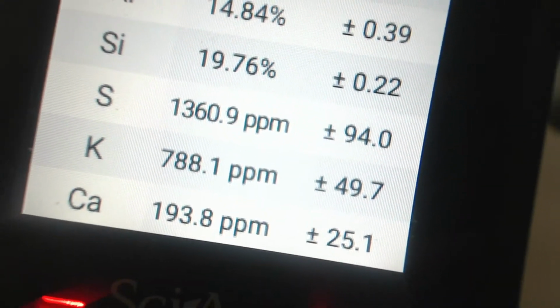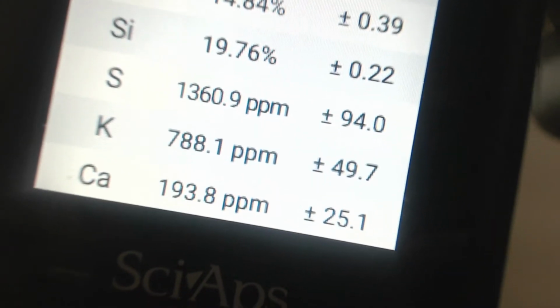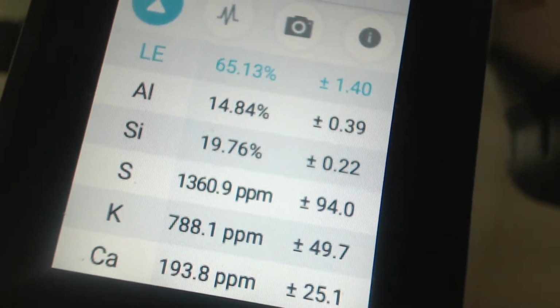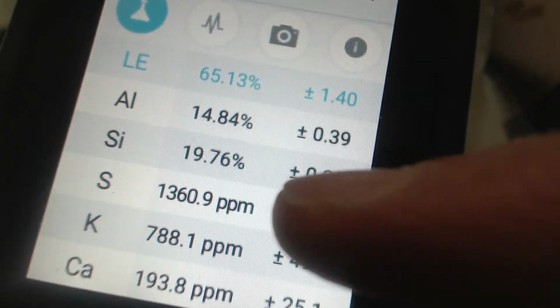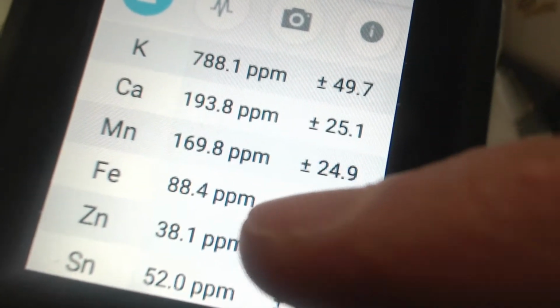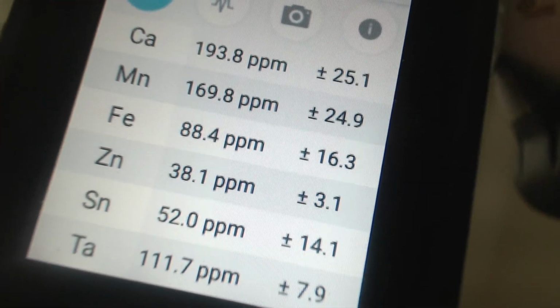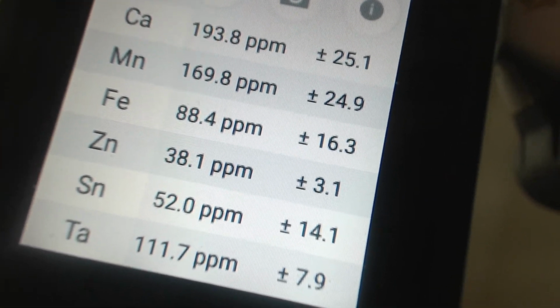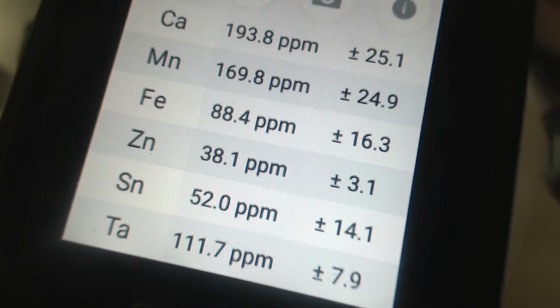So first off, you see aluminum, silicon up around 15-20%. Then you see some trace level elements down below, down to ppm levels. And this was a really quick test, only a few seconds.